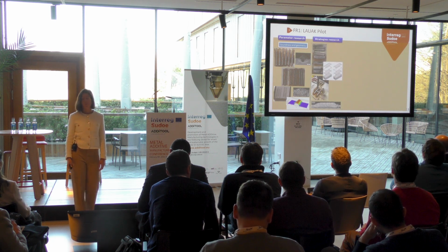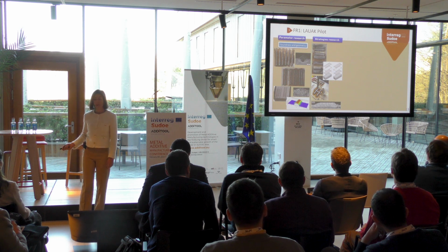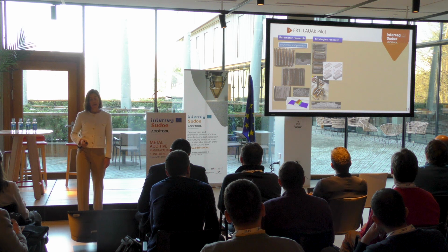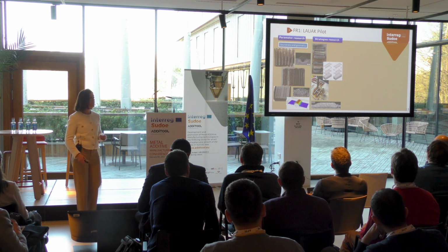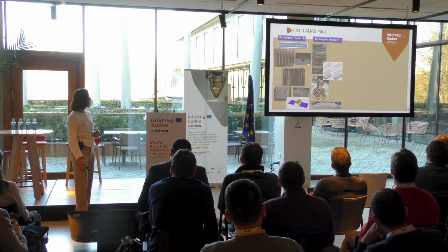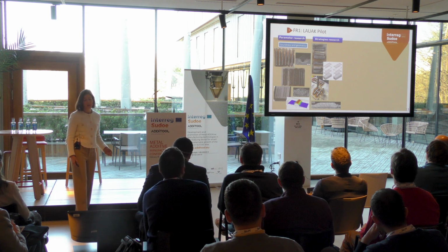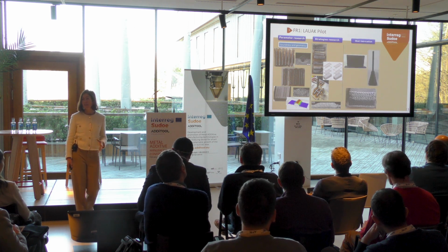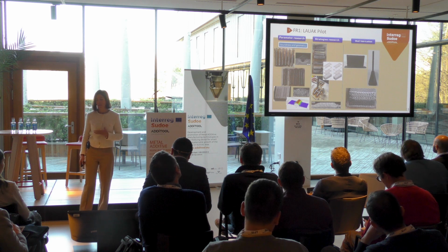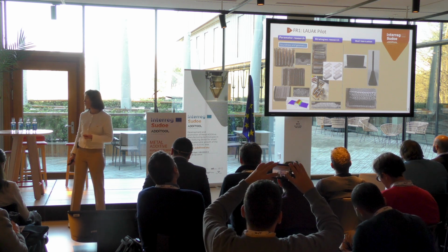Then, with those parameters, we studied the strategies within each layer, between layers, and also at intersections. Once we had all this data, we manufactured simple walls.